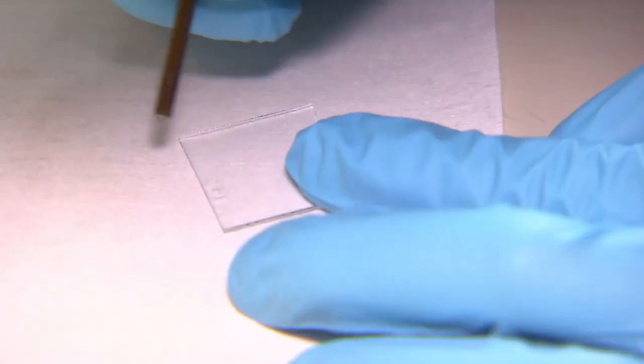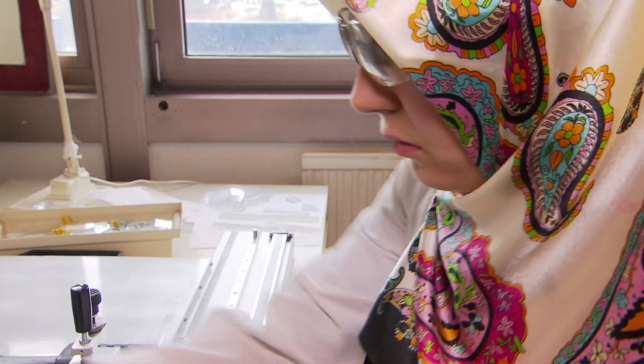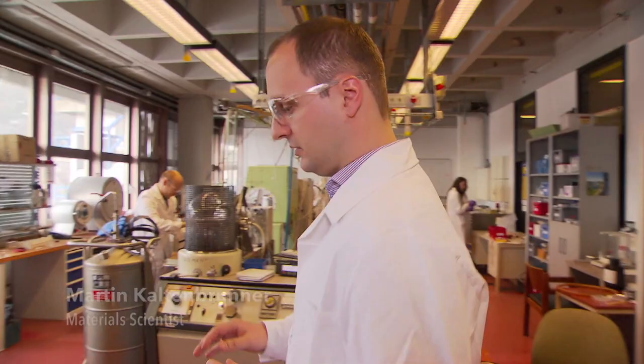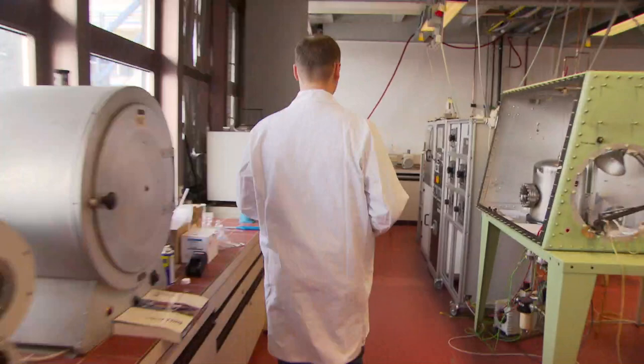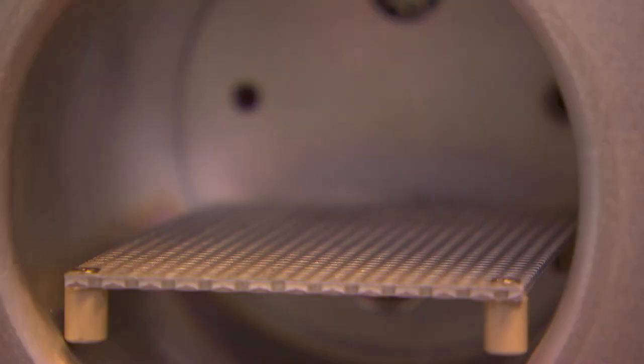Where and how are these colorful solar cells made? We're in the lab where the solar cells are made. You start with a substrate. When you start out, that's often a piece of glass coated in a conductive electrode. We first clean the glass with different solvents, then we dry it in nitrogen, and then we treat the surface with oxygen plasma. That's so we can apply the layers thinly and uniformly.